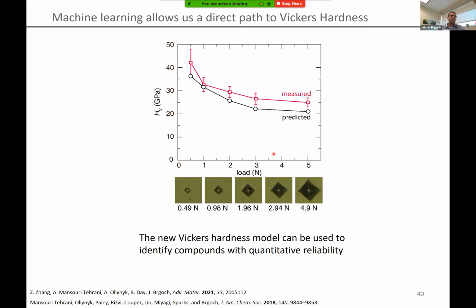So what does that mean for our previously discovered compound? Here was the experimental measurement, and here is our Vickers hardness prediction using XGBoost. You can see nearly quantitative agreement, just a little bit of underestimation. More importantly, we're able to identify what our load response curve looks like.